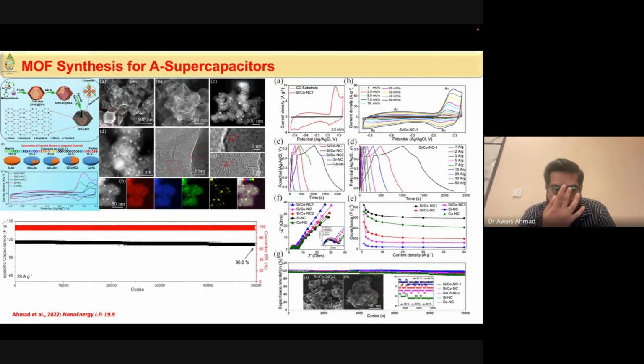And in that scenario, we also designed the double layer MOF, which was very tough to design, because it's very tough to organize such double layer MOFs and stabilize them, because you are mixing two MOFs. So we designed ZIF-8 and ZIF-67, two birds with one stone, and we get asymmetric. You can see here the peaks. It's the asymmetric supercapacitor, and at the end we get 98.6% capacitance retention with 50,000 cycles. And it was one of the best articles we have ever produced, with 50,000 cycles.